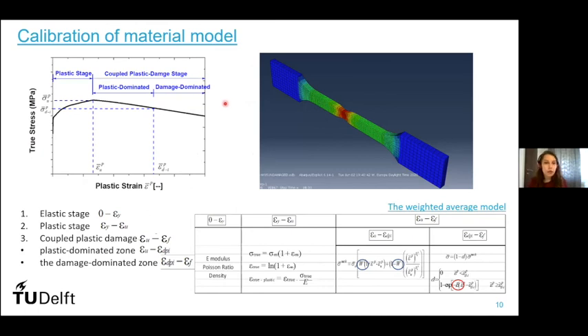Of course, I had to calibrate the material model. In the elastic stage, I introduced the E-modulus, Poisson ratio and density in the model. Then for the plastic stage, I calculated the true stress and the true plastic strains. Moreover, in the coupled plastic damage stage, I calibrated the damage material parameters W and B, using the weighted average model.